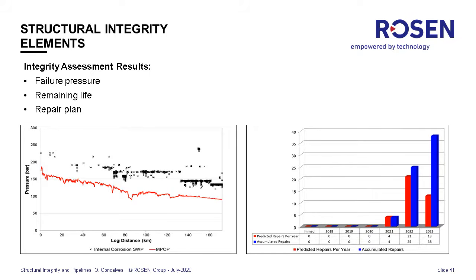But of course, if the feature you're looking at can evolve with time, it can grow. At some point, the failure pressure might decrease and reach the red line. And as a result, it's important to understand how quick this growth can take place to reach the critical value, and then we can establish a schedule of how many of those features need to be verified and repaired over the course of the next year. So that's the usual integrity management approach.